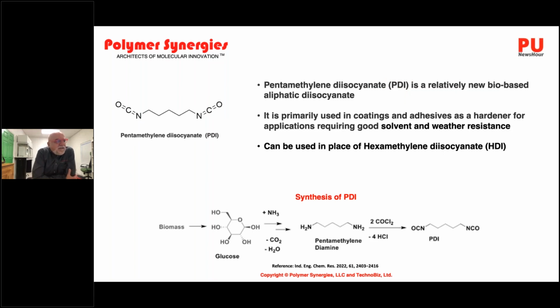There's an aliphatic isocyanate, pentamethylene diisocyanate, which is a relatively new bio-based aliphatic diisocyanate. I believe it was only introduced somewhere around 2015 or 2016. And it's primarily used in coating and adhesive applications because it's an aliphatic isocyanate. So you want to use it in applications requiring good solvent and weather resistance. And it can be used to replace hexamethylene diisocyanate. So it is a bio-based isocyanate that can replace hexamethylene diisocyanate.